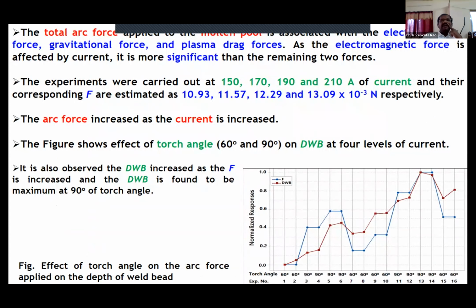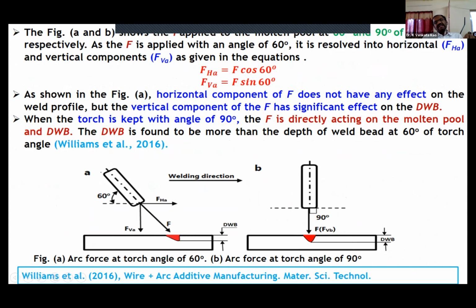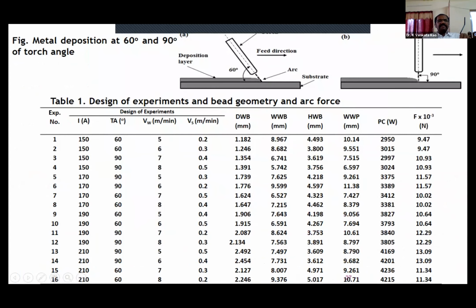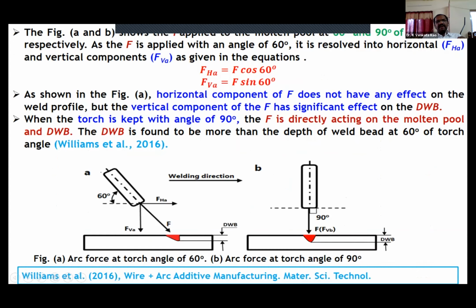Now here, the effect of the arc force. The effect of the arc force at 60 degrees. See this one. See, the welding torch is kept at 60 degrees here. Welding torch is kept at 90 degrees here. This design of experiments was conducted at 60 degrees and 90 degrees, and the effect of arc force is shown.